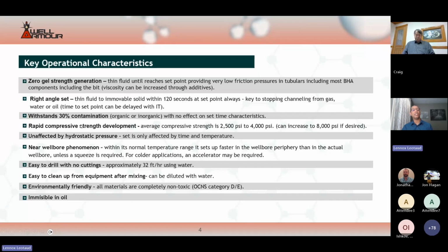Well Armour system can withstand contamination up to 30%, whether that's organic or inorganic contamination, and it's not going to affect, say, the ultimate compressive strength development of that Well Armour slurry. Let's just say your design compressive strength was 3,000 psi. With as much as 30% contamination, you're still going to achieve fairly close to that design compressive strength. Once the set is attained, the Well Armour slurry builds compressive strength rapidly. Typical compressive strength is between 2,500 to 4,000 psi. But per slurry design, you can achieve higher values than that.